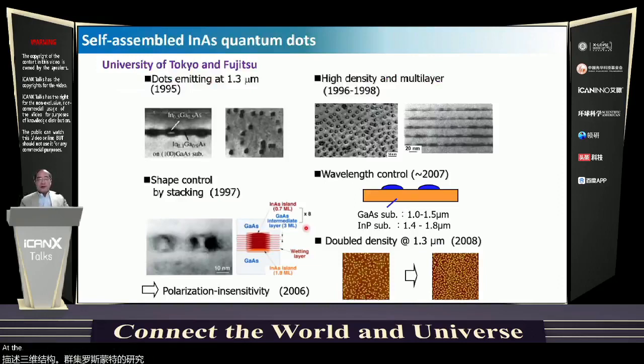At the University of Tokyo, in collaboration with Fujitsu, we also started to work on the formation of quantum dot structures, focusing on 1.3 micron. And in 1995, exactly speaking, Fujitsu found quantum dot formations emitting at 1.3 micron. Higher density than before, with multiple layers, was realized like this. And also, in addition to isolated quantum dot structures, shape control by stacking can be realized like this.